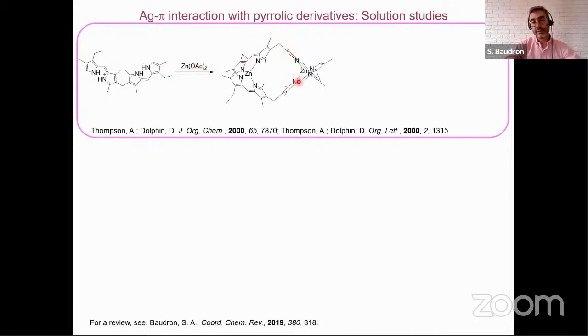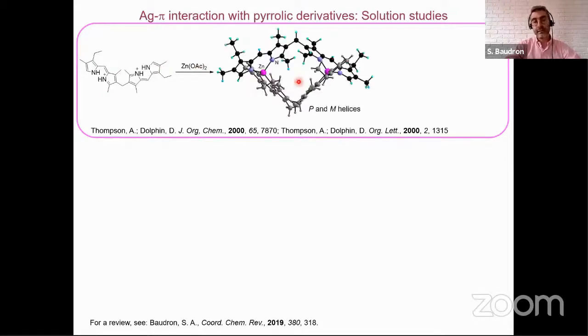You have here a schematic representation of this helicate, and in this case, a crystal structure of this compound, with one strand in black and one strand in gray. They were trying to investigate whether in these complexes you can form more of a P or the M helix, whether you can have an enantiomeric enrichment of those helices. To do that, they studied by NMR the assembly of those complexes with silver salt in the presence of a chiral lanthanide salt. They showed in their NMR investigation that indeed there was an interaction of a silver cation to the carbon-carbon double bond in this system.